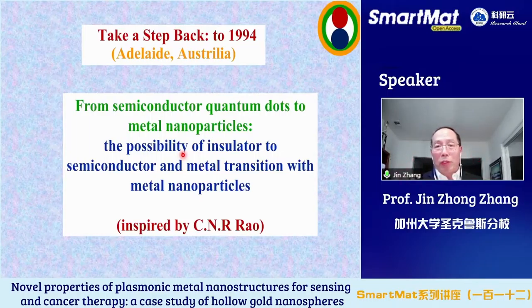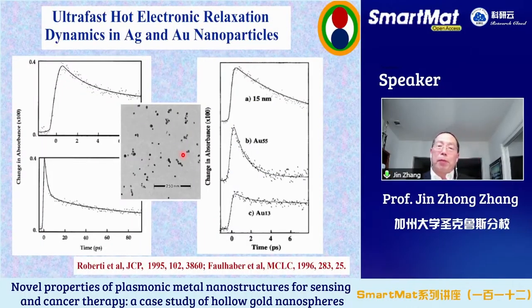So we made some silver nanoparticles first. We put them in the laser. We saw a beautiful signal. But then we didn't know what we were looking at, because when we looked into the literature, there was no publication. So these are the first two papers published, to our knowledge, on metal nanoparticles of silver and gold. In between our two papers, a paper from France, from Bigot's lab, on a femtosecond study of copper nanoparticles in glass came out. So essentially, without getting into the details, we are seeing a very fast relaxation of 1 picosecond due to electron-phonon coupling. Then we have hundreds of picoseconds of decay due to phonon cooling into the solvent.